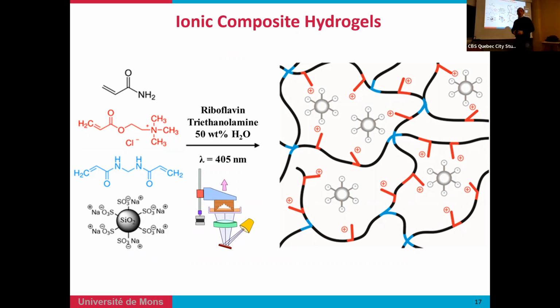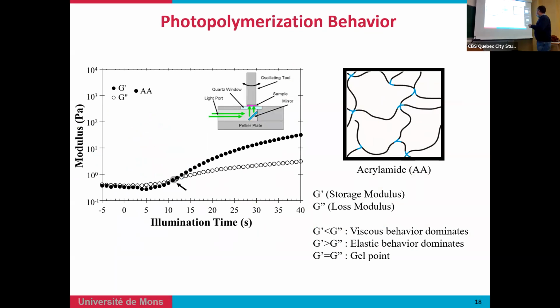Of course, when you try to implement that by 3D printing, you need to select the right photopolymerization conditions, so you need to use the right photoinitiator that in this case also works in water due to lack of solubility for the system. And of course we demonstrate the photopolymerization, as already mentioned, based on the relation with the storage modulus, which you can obtain by this photorheology system against the illumination time.